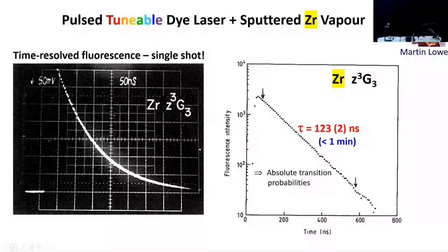So the first thing we tried to do was just some time-resolved fluorescence on zirconium, which is a highly refractory element. This shows just a single-shot decay curve. You take the logarithm and just plot it, you get a lifetime of 123 nanoseconds, about 2% accuracy, and we get the lifetime out in less than a minute. And so we could study a lot of levels and a lot of elements very, very quickly.